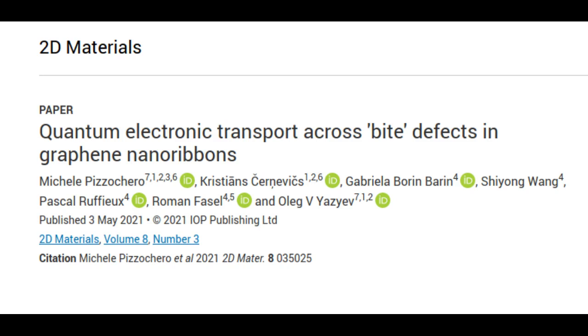In the 2D Materials paper, the researchers combine experimental and theoretical approaches to investigate defects in bottom-up AGNRs. Scanning tunneling and atomic force microscopies first allowed the researchers to identify missing benzene rings at the edges as a very common defect in 9AGNRs and to estimate both the density and the spatial distribution of these imperfections, which they have dubbed bite defects. They quantified the density and found that they have a strong tendency to aggregate.